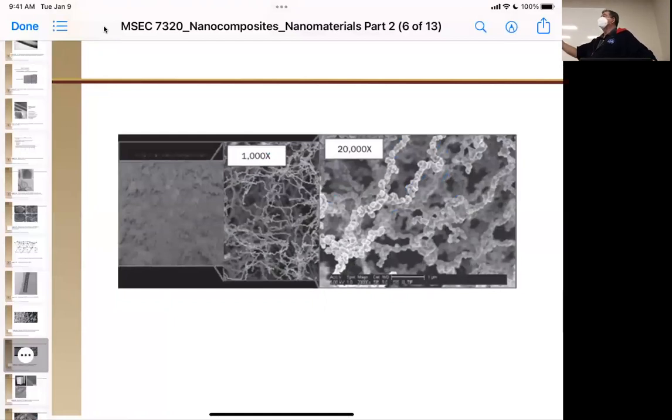So it's used in processes where you're looking for very high conductivity, electrical and thermal, but it oxidizes over time and oxidizes at the interface. The nickel, while it doesn't have as high electrical or thermal conductivity as the silver, does have much better environmental stability. So you can take these materials, process them in your polymers, and then even pyrolyze the polymer out to get this porous microstructure or nanostructure.